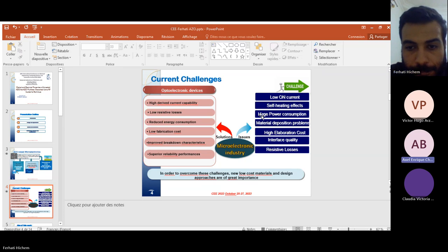The thickness of the structure can be a problem for this application related to high power. Yes. The thickness of the introduced Ag thin film, silver thin film, can modulate the electrical and optical behavior of the multilayer structure, where it is recommended to use an ultra thin film of about 8 to 10 nanometers. And this thickness can introduce an issue also in medium temperature, I think.